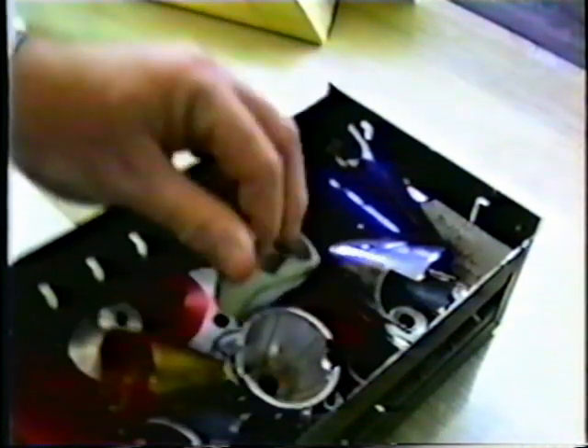This is a long nose spinner that I made that the paint is sticking to pretty well. Sticking the paint to aluminum, the best way to do it is to anodize the aluminum, scuff it up a little, use auto primer first. If you can't anodize, scuff it up with a 80 grit paper, put two coats of primer, sand the primer, and you'll usually have it last one season before it starts to chip and peel off.